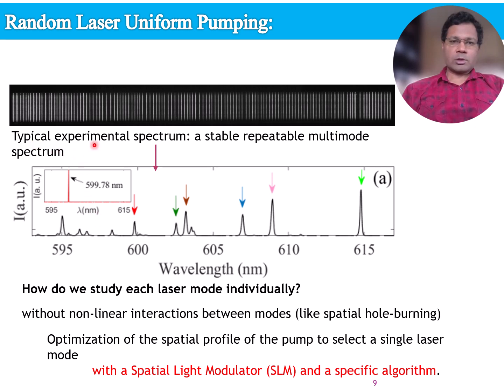The disorder structure was optically pumped using a laser strip from a frequency doubled Nd:YAG laser, which is a picosecond laser emitting at 532 nanometer. When the dimensions of the pump exactly match the sample size, there is enough power to overcome the losses and this produces lasing. This produced sharp lasing peaks over a weak spontaneous emission background. This is something that has been demonstrated in various random lasers, as I discussed in previous slides. Here you can see that there are multiple modes.